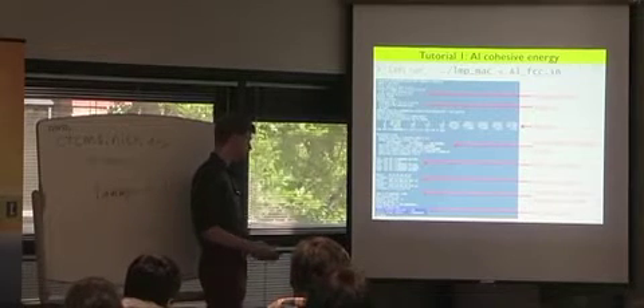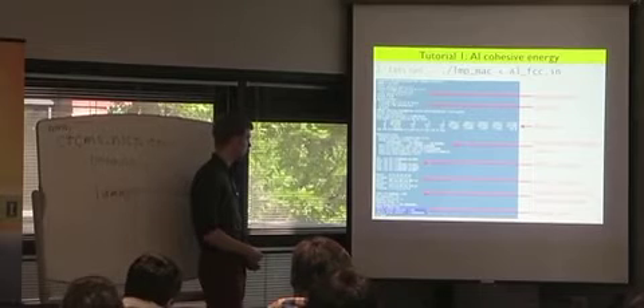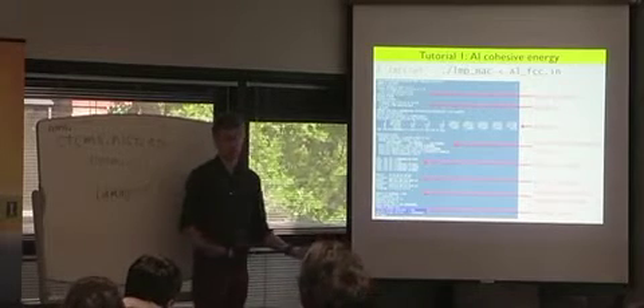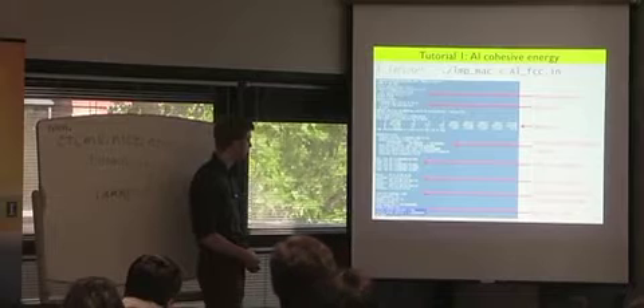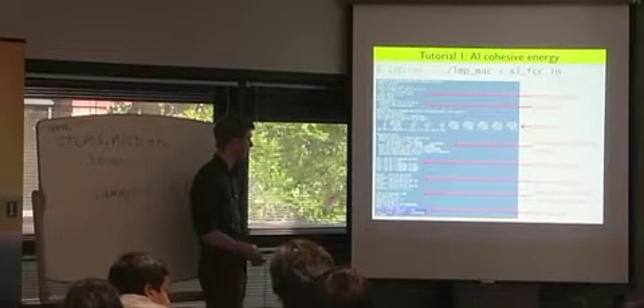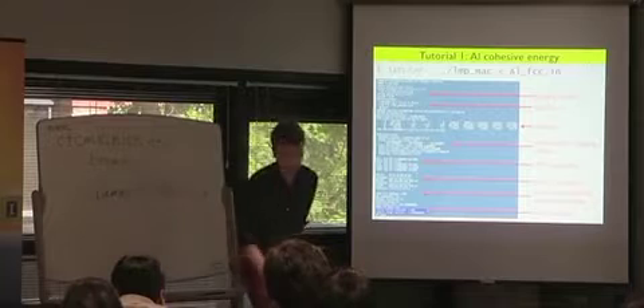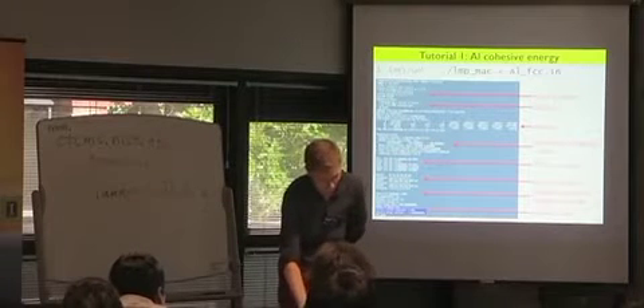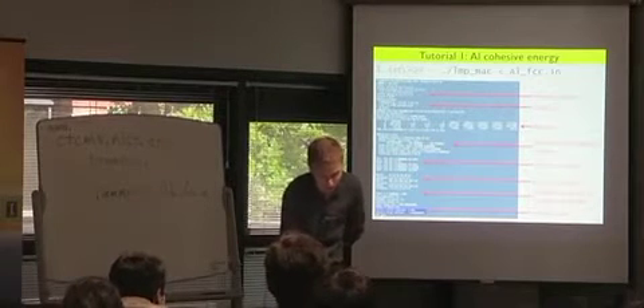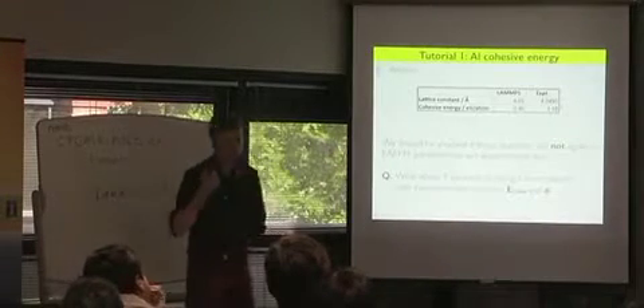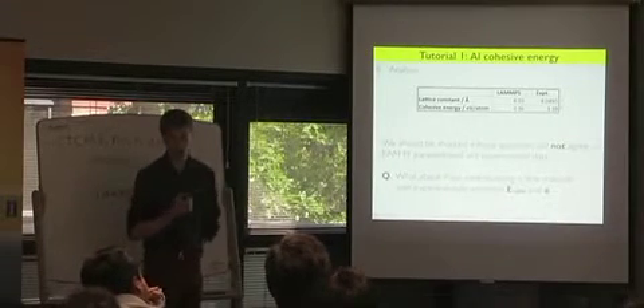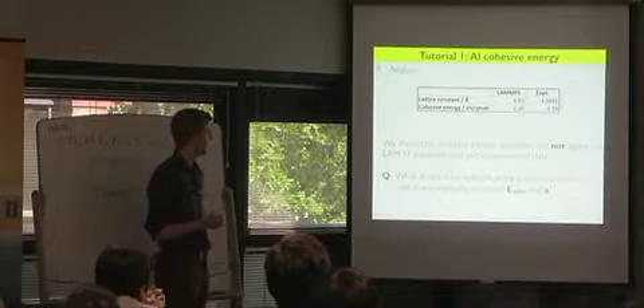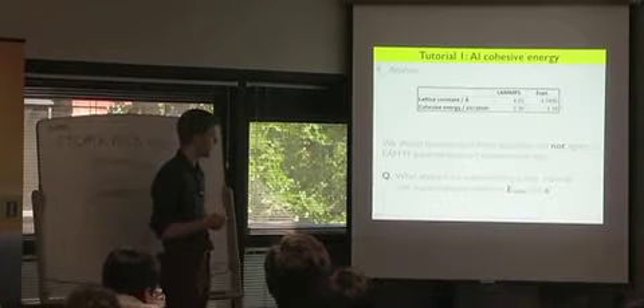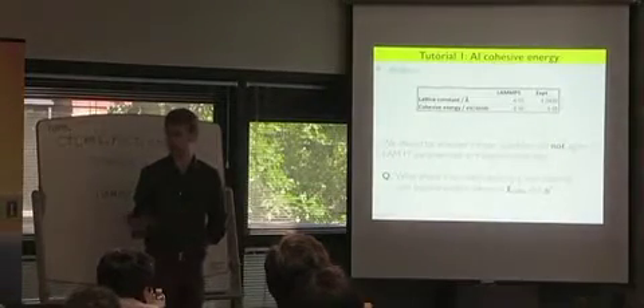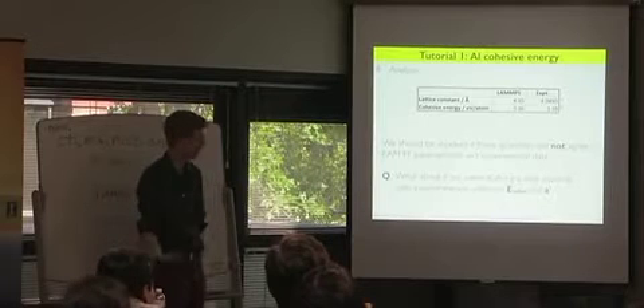Okay, then we asked LAMMPS to print some things for us. We asked it to print the total energy and number of atoms, and then what I've highlighted here, which is why we did this simulation in the first place, which was the lattice constant in angstroms and the cohesive energy in electron volts per atom. Depending on how you ran your simulation, you should probably get very similar answers to me, which was 4.05. Very close to experiment, 4.0495 for the lattice constant in angstroms, and the cohesive energy negative 3.36, which is very close to the experimental value of negative 3.39. So we can all pat ourselves on the back and say what a wonderful job we did with molecular dynamics.